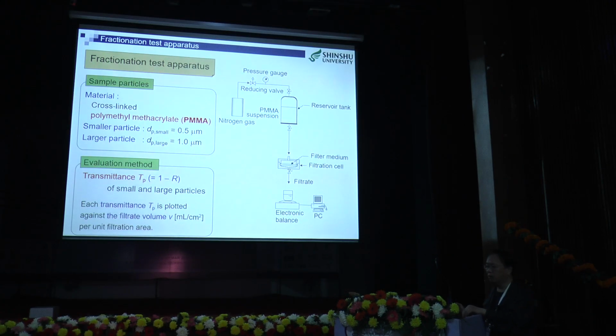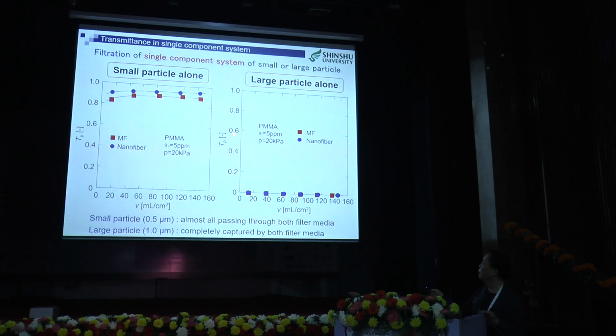This is a schematic diagram of fractionation test apparatus, which is substantially the same as the filtration test apparatus. We use two types of cross-linked polymethyl methacrylate PMMA particles. Smaller particle diameter is 0.5 micrometer. The larger particle is 1.0 micrometer size. To evaluate the fractionation performance, we use transmittance TP. Please note, it's not R. TP equals 1 minus R. We use the transmittance plotted against filtration volume.